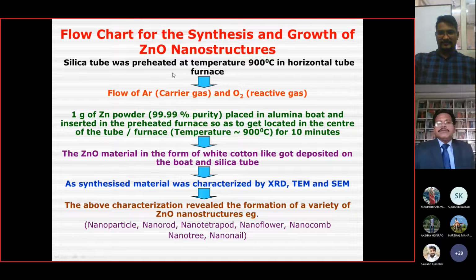First of all, we have to take the silica tube at a particular temperature, 900 degrees Celsius, and make it clean and dry. After that, we have to pass argon gas and oxygen. In this case, 1 gram of high purity zinc powder we have to place in an alumina boat, and then keep it in the preheated furnace at 900 degrees Celsius for 10 minutes. After that, zinc oxide material in the form of white cotton-like thread is deposited in the silica tube or the crucible. These synthesized particles can be characterized by using TEM, SEM, and XRD. And after characterization, we can use this material for different purposes.